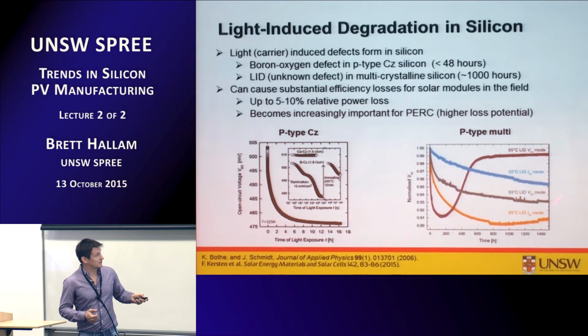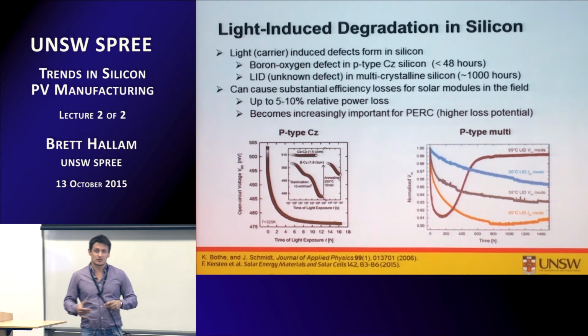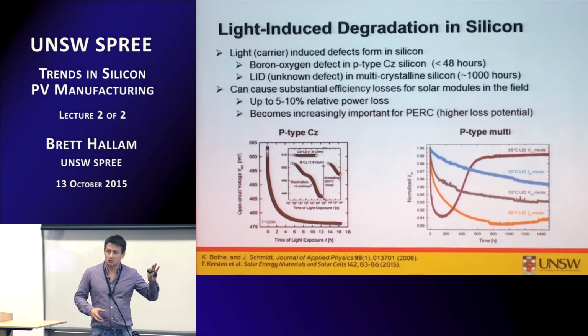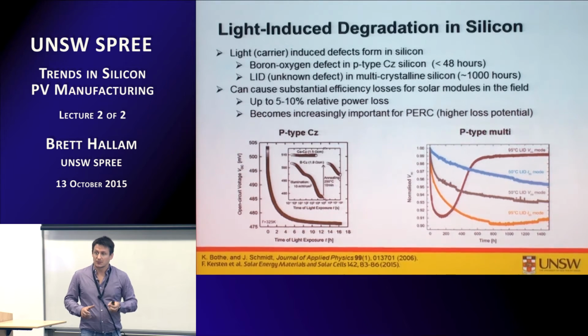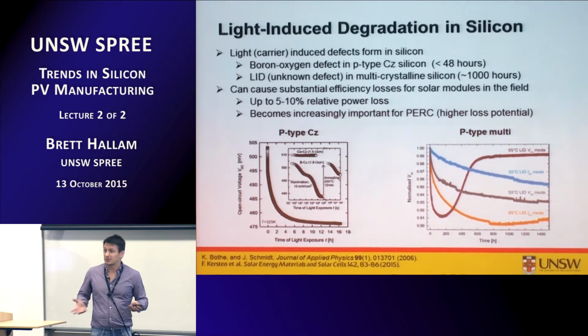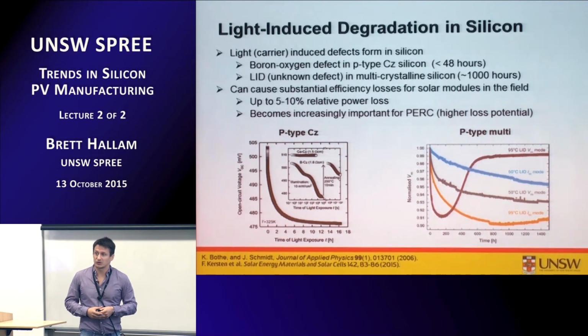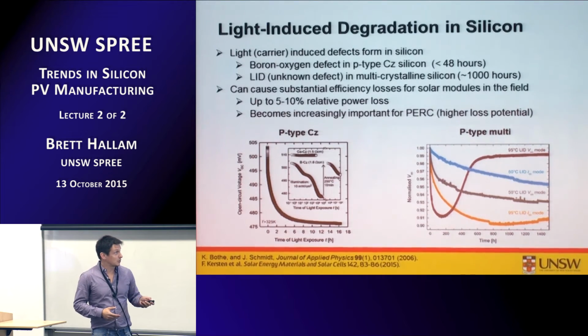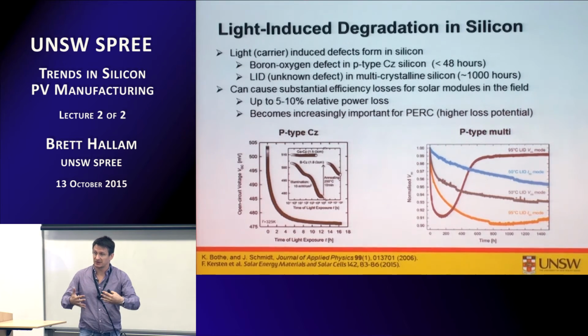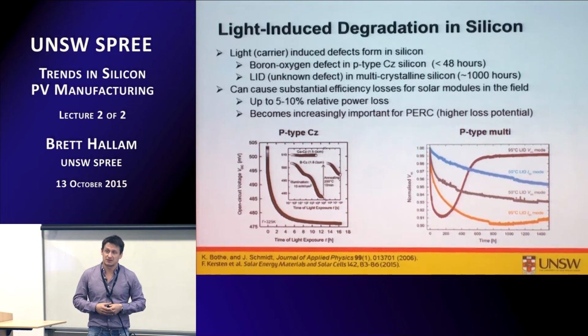You'll see here a graph. Don't worry about this, where this increases again. I'll go over that shortly. But the generation of the defects as the VOC reduces is looking towards 1,000 hours, and it can still be going down. So this means that these multi modules going out in the field, you won't know about this in a couple of days like you will in the monocrystalline modules. It can take weeks, etc., to fully generate these defects before you get the full effect of the efficiency loss.